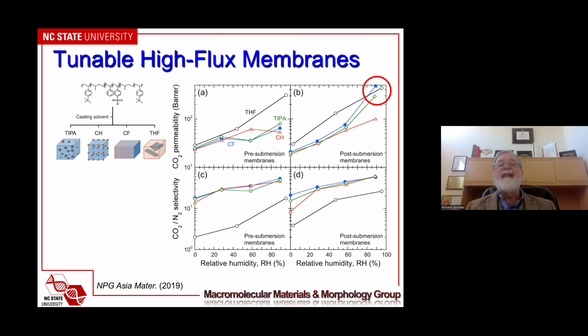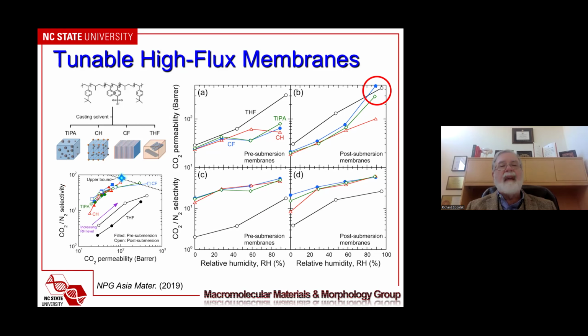If we take these materials and simply put them into liquid water, we can induce a non-thermodynamic morphological transition such that we now have a greater degree of interconnected hydrophilic channels. And by doing so, the permeability of CO2 increases significantly up to about 500 barrer, whereas the selectivity really doesn't change. And what that does is it actually gets us over that upper bound line that I showed you in the performance graph. It's not a significant increase over the upper bound, but it does show that it's possible to get above that upper bound using these materials.